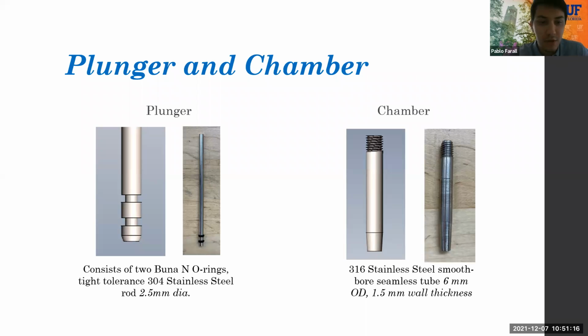And for these 2 parts, the chamber is 6 millimeters in outside diameter and 3 millimeters in inner diameter and 48.7 millimeters in length. And the plunger is 2.5 millimeters in diameter, 69.5 millimeters in length. It has 2 machined grooves that will be used for the 2 O-rings, and it has a tapered end that allows for an easy insertion into the chamber. And from testing, this O-ring and plunger combination showed no signs of leakage.